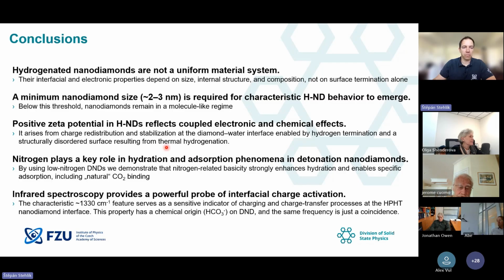And the zeta potential is quite probably arising from this charge redistribution and stabilization at the diamond-water interface, which is enabled by the hydrogen termination, but the structurally disordered surface is also important, and this is the result of the thermal hydrogenation. Nitrogen was revealed to play a key role and be responsible for this tight, specific hydration and adsorption of CO2. And we also tried to disentangle this Raman-like feature in IR spectroscopy, where we showed that it has a different origin, chemical on DND and physical on the HPHT nanodiamonds, and the same frequency is just a coincidence.